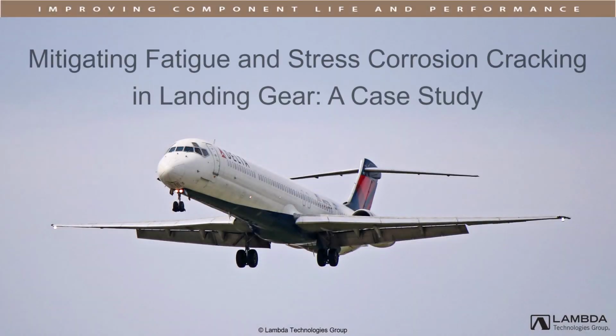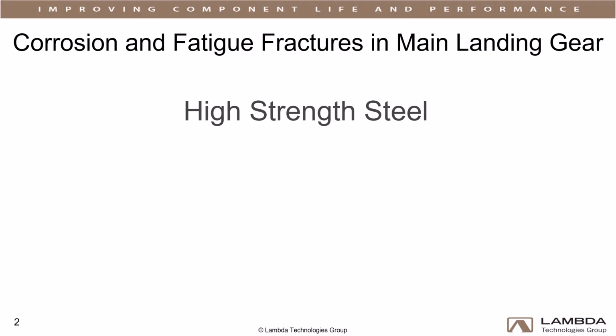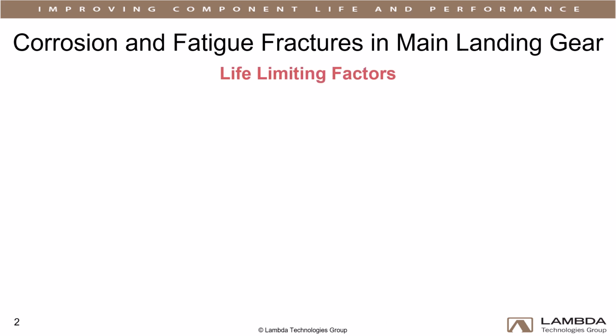The following case study is an example of how engineered residual compression successfully mitigates gear walk, corrosion fatigue, and stress corrosion cracking in landing gear. Landing gear is manufactured from high-strength 300M steel due to its exceptional durability and fracture resistance. Despite this material's inherent strength, landing gear is still life-limited from stress corrosion cracking, SCC for short, corrosion fatigue, and fracture from vibratory stresses.